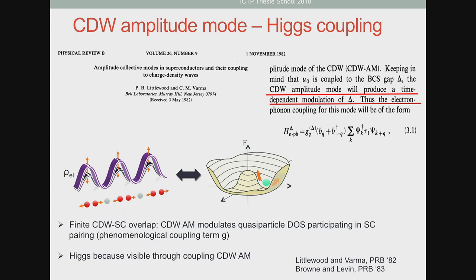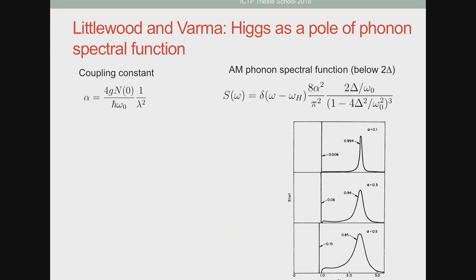Okay, so the idea in this scenario is that the Higgs mode would appear as a sort of sideband of the amplitude mode of the charge density wave phonon, essentially. So this is the calculation in that paper. They calculate the phonon spectral function, and by coupling it to the Higgs mode of the superconductor, the phonon spectral function acquires a new pole. And this new pole will generically appear below 2 delta.